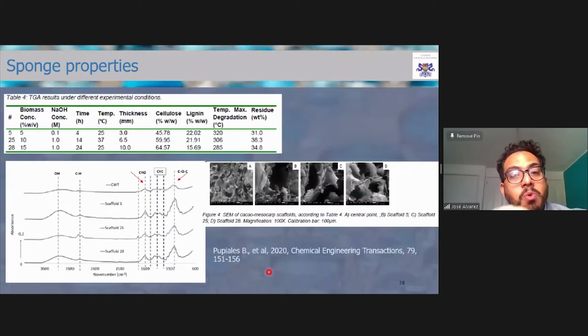So after that, we decided to look into more detail at the sodium hydroxide treatment, and we created sponges with different compositions in terms of cellulose and lignin. We saw very important differences in the thermal properties, temperature of maximum degradation and residues for the thermogravimetric analysis. We also did some FTIR, and we saw the disappearance of peaks that are associated with lignin. So what the sodium hydroxide does is it swells and breaks this lignin structure, which gives more rigidity to the material and also lowers the capacity for biodegradation. And so our idea was to eliminate as much lignin as we could and keep more of the cellulose. So we saw some of those peaks that are shown here with the red arrows disappear or diminish.